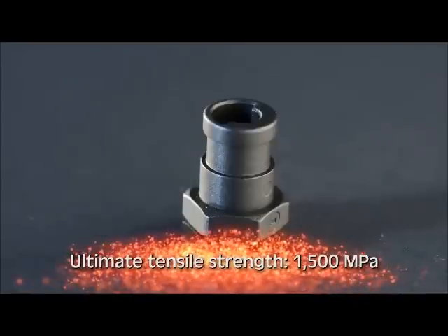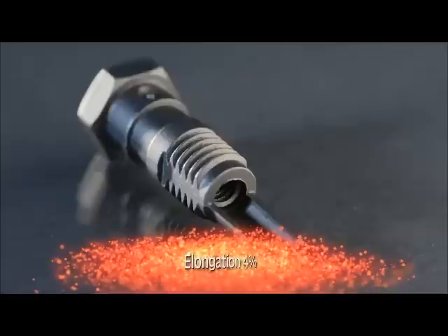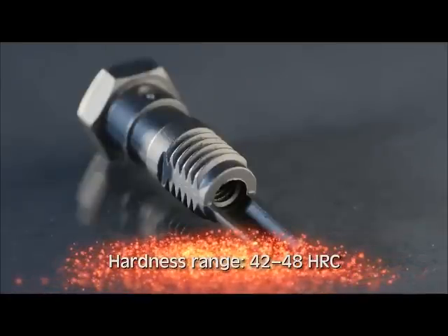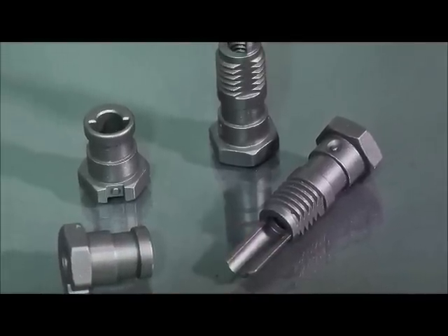Both parts are fabricated to net shape, with all dimensions achieved in the as-MIM condition. This includes the threads, which are formed through auto-unscrewing in the tooling. The fabricator delivers 320,000 pieces annually.